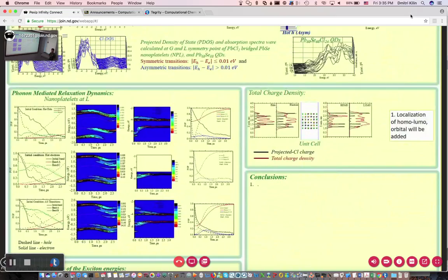Again, this is at 0 Kelvin? Is it averaged over the ensemble? The average over the ensemble, both HOMO and LUMO and your initial one. Okay, so it's a 300 Kelvin kind of average distribution over the ensemble. So you compute the distribution at each time step and then add them together? And project it to the z direction. First project it to the z direction and then average, and then add them together. If you would take partial charges along the trajectory, you will kill the computer.